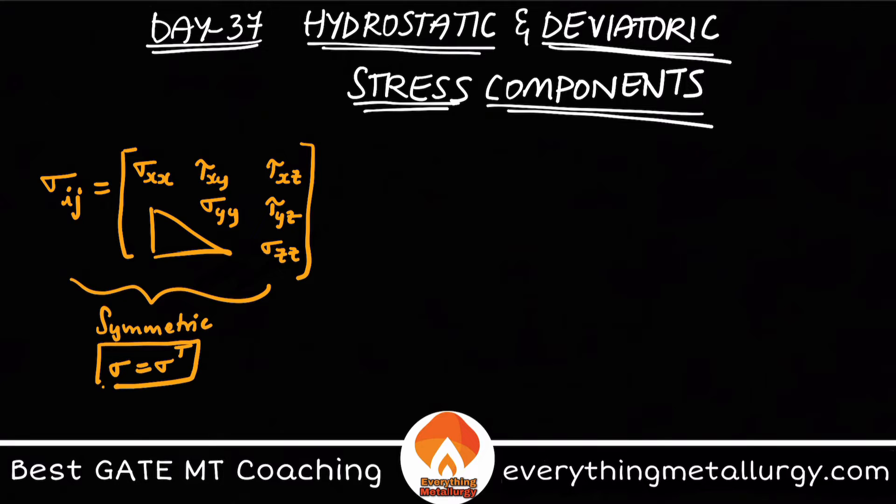This is my symmetric tensor. Sigma will always be equal to sigma transpose. Using this, we know that any symmetric matrix can be easily split into two parts. Similarly here, we usually tend to split our stress tensor into two parts as you can already see: one is the hydrostatic component or mean stress, and the other is called the deviatoric part or deviatoric stress component.